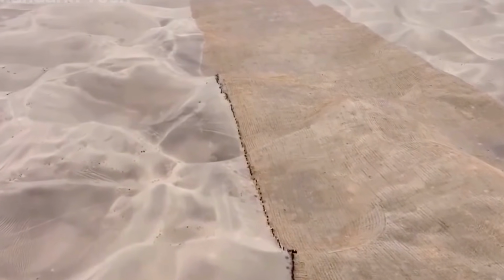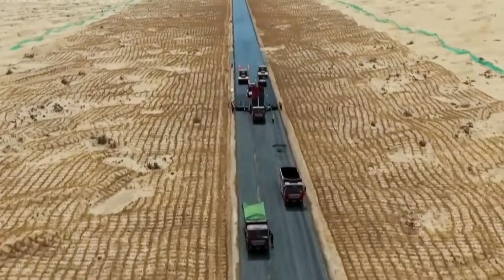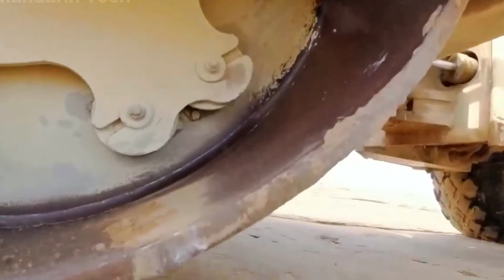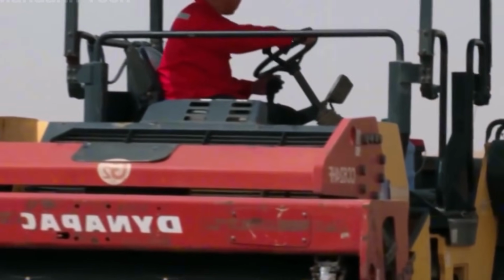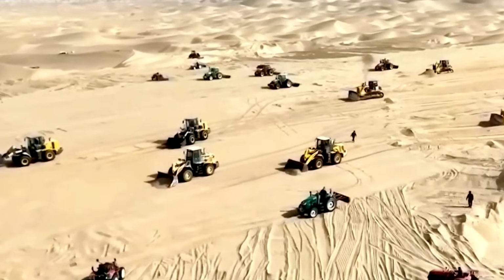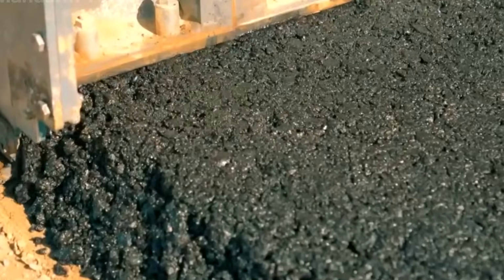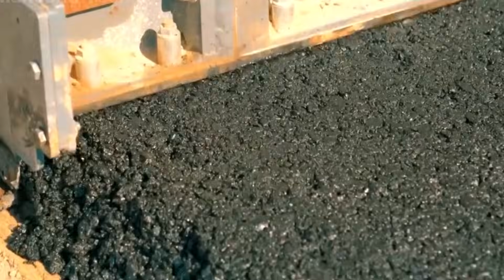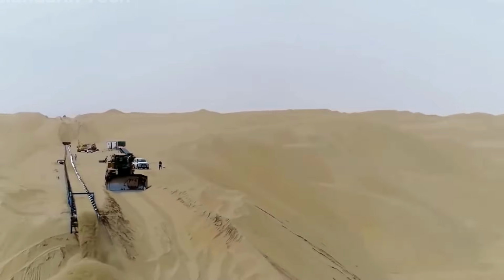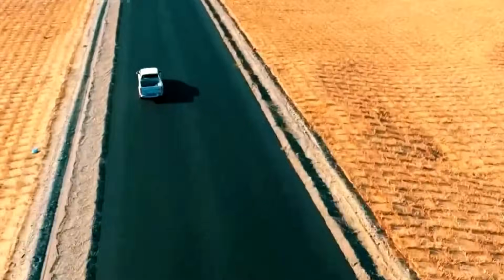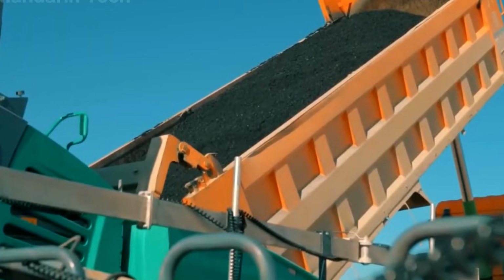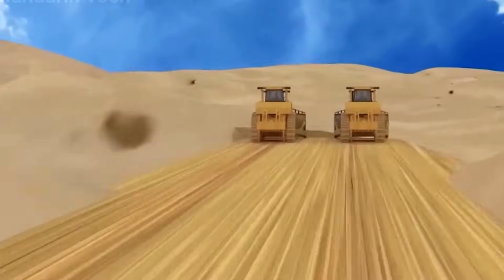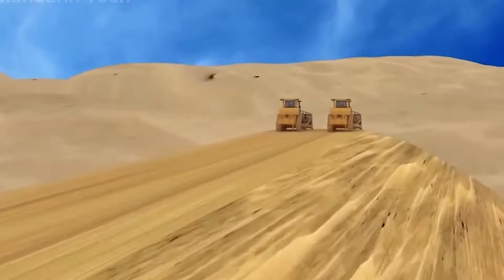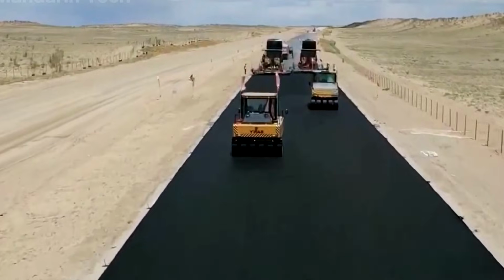Unlike the silent dunes, portable asphalt plants roar to life at the edge of the desert, heating stone and polymer-modified bitumen to nearly 170 degrees Celsius. Insulated tankers deliver the hot mix non-stop to the paving machines waiting on the line. It is visible how each paver spreads the glowing asphalt in layers about 6 centimeters thick. Steel rollers follow close behind in a tight choreography, compacting the material before it cools.